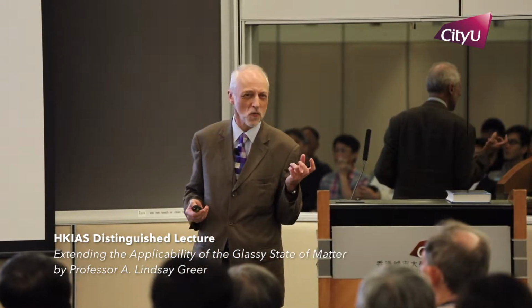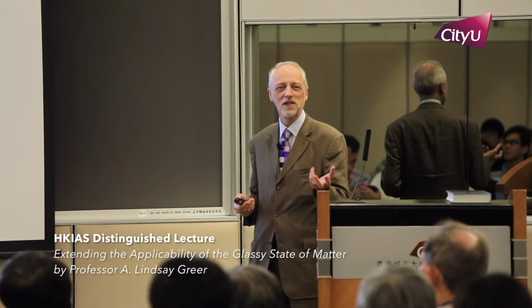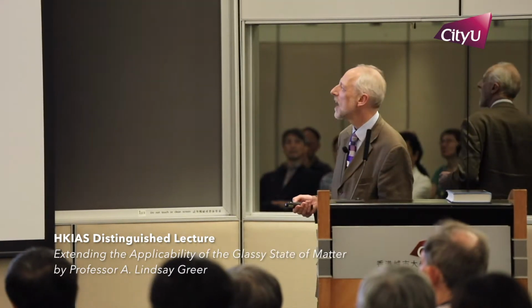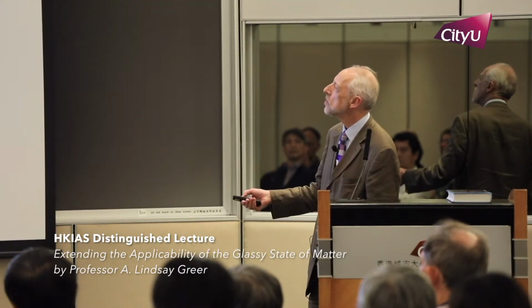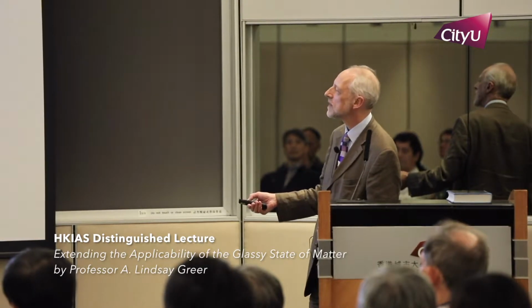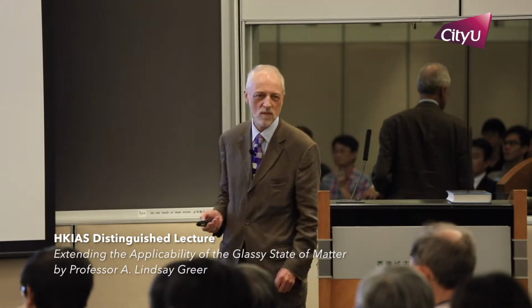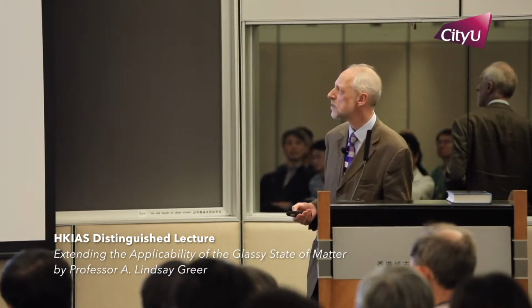Furthermore, a liquid metal, classically at its melting point, has a viscosity very similar to water. So the atoms are extremely mobile. But if you put some alloying elements in, the system might get a little bit confused about what sort of crystal it would want to make. And so for a simple binary system, you can adjust things so that you can get a glassy state, but you need a quite high cooling rate, up to of the order of 1,000,000 degrees per second.